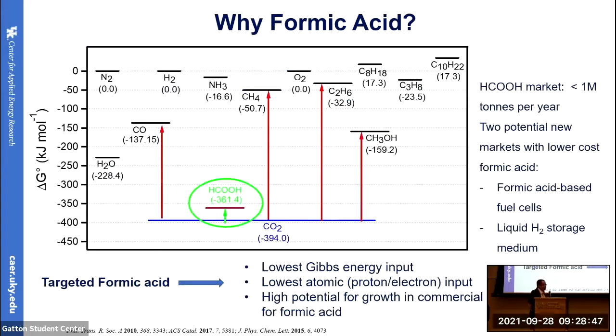Looking at this plot, which gives free energy for different molecules, we can say formic acid is very close to carbon dioxide. So it needs the lowest Gibbs energy input for conversion of CO2 to formic acid. Also, it can be converted using very cheap materials, easily water, and just what we need is a suitable catalyst.